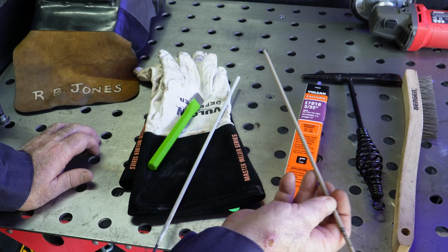But before I start, the one thing you want to look for is, once you start this arc, you want to form your puddle. One of the first things you've got to learn is how to identify the puddle from the slag that's running off of it. So the slag is going to be pouring off the backside. That's the reason you've got to angle your rod like this. It's not as critical on flat, this angle. I normally go somewhere right in here or maybe in here. But when you get in overhead, I'll explain that when I get to it. At any rate, you want to look at that glossy puddle, and you'll see the slag blowing behind it. The arc force from this rod will push the slag off the molten metal, and all you do is watch that puddle, try to keep it the same height, width, depth, everything about it as you advance.